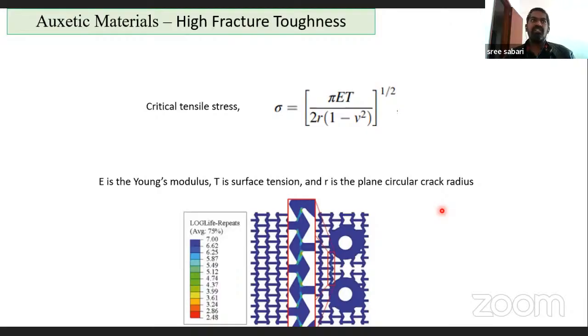In the conventional material, less energy is required for the crack opening. So you consider this is a crack, you have a gap here. In order to propagate this crack to a bigger size, you need to open it. So on opening of this region, the crack will propagate. For the auxetic material, the energy required for crack propagation is higher. So in that way, it offers higher fracture toughness.